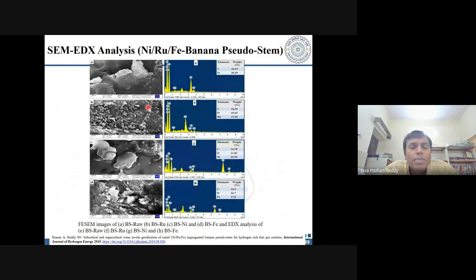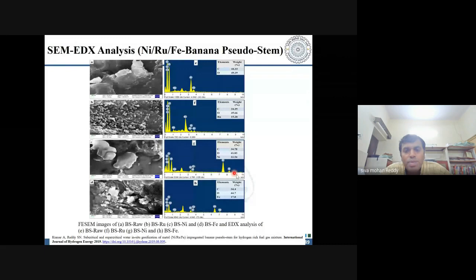Okay, so to further confirm the presence of these metals on the biomass matrix, we have done the SEM EDX analysis, that is, scanning electron microscopy and energy dispersive X-ray analysis, to quantify and to understand the morphology and structure. You see that your structure is very smooth for a raw banana pseudostem. Now, as soon as we perform the impregnation experiments, we see that the surface becomes rough and distorted with the loading of metals onto the surface. A nickel content as high as 22.54 weight percent has been obtained. And you see that out of all the three metals, the nickel loading has been high, followed by iron and ruthenium that we are talking about.